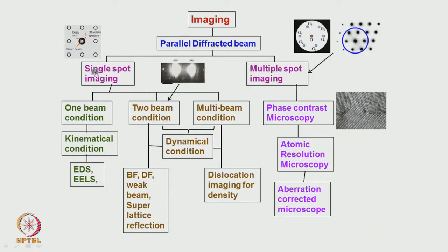In imaging also, I talked about a simple bright field and dark field from a parallel diffracted beam. In a parallel diffracted beam, there are many ways in which it could be used. If we choose the beam in such a way that only the central spot is bright and all other spots are weak, I call it single spot imaging. In this case, only one beam is strong, and this condition we call the kinematical condition. That means all diffracted spots are weak, and essentially only one scattering event is taking place. That is the condition under which we should do EDS or EELS in a microscope. This is the way it has to be done.